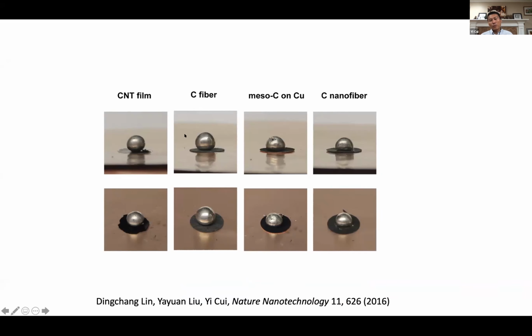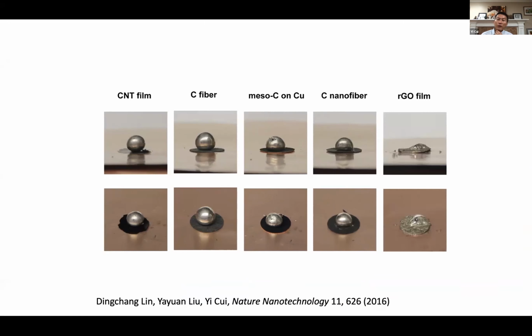You see, once you melt lithium and try to get lithium going into those structures, they don't like to wet. Lithium in the molten state, this is inside a glove box, of course, because molten lithium is dangerous. You need to do it in that environment. They don't like to wet these materials. So when we tried graphene oxide, the lithium metal melt wets inside. This wetting phenomenon, we call by a new term, lithiophilic, in analogy to hydrophilic. The opposite phenomenon will be lithiophobic, in analogy to hydrophobic.